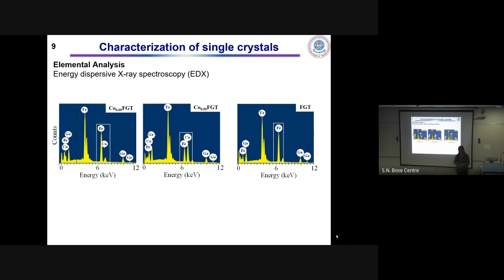But without cobalt you could also vary the iron concentration a lot, from 2.8 to 3.2, without putting any cobalt. If you take extra iron in your CVT, you could get more, and if you take less, you get less. Then you have to look at many crystals, and you can collect that series by performing reactions on it.